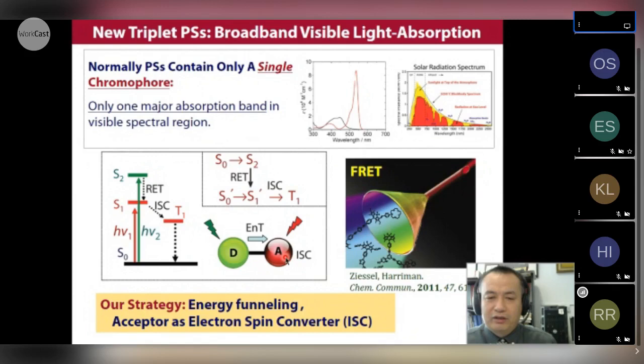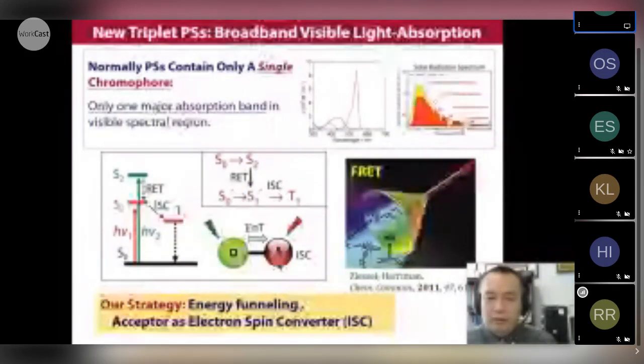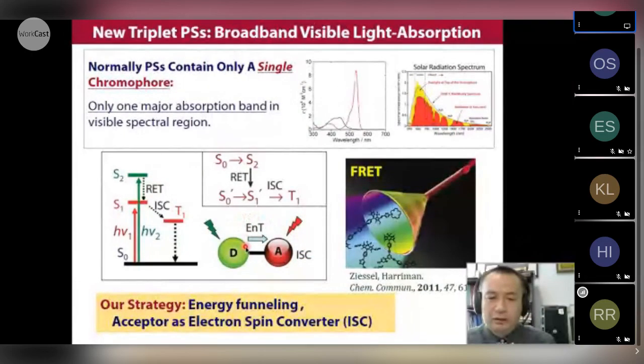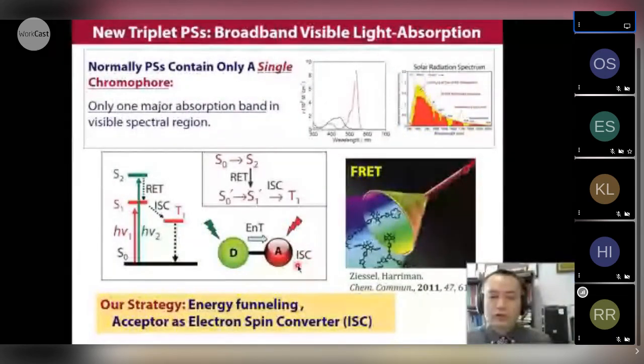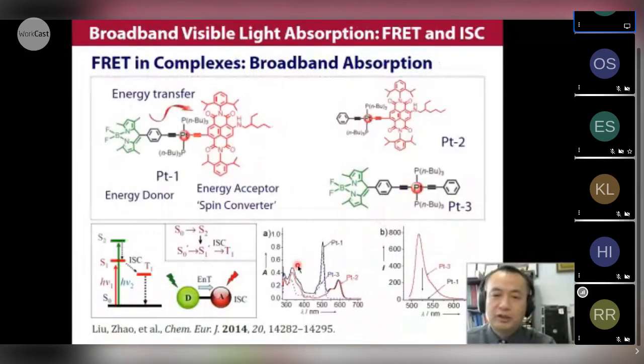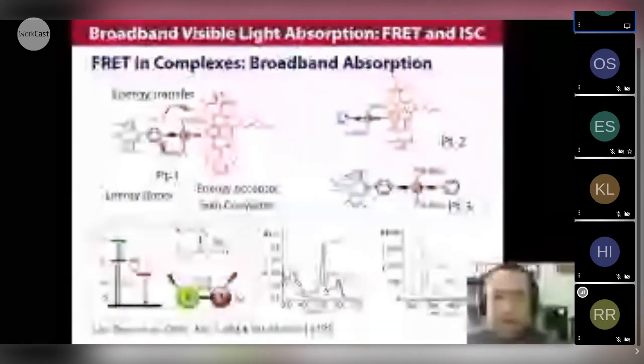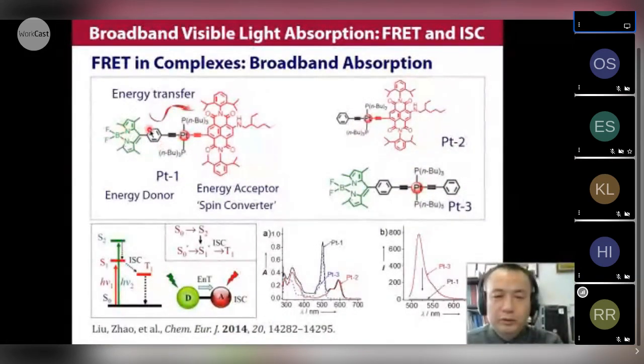But here we make a further step. We modified the structure of energy acceptor to have efficient intersystem crossing. We don't need a strong fluorescence emission, but we need efficient intersystem crossing to transform the broadband excitation energy to the triplet energy. So this is our basic idea. So we prepared this complex. It contains two parts, the BODIPY part and this NDI part. These two parts give different absorption. So we cover a large part of the visible region.